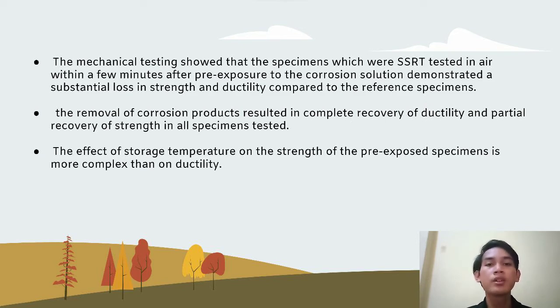The removal of corrosion products resulted in complete recovery of ductility and partial recovery of strength in all specimens tested. The effect of storage temperature on the strength of pre-exposed specimens is more complex than on ductility.